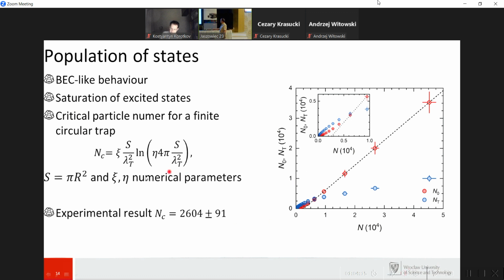So experimental critical value for this geometry is 2,600 particles. And this exactly gives the temperature as we measured of the Bose-Einstein distribution at the threshold. So it is not in equilibrium, but it looks like everything - we open the textbook and everything fits.